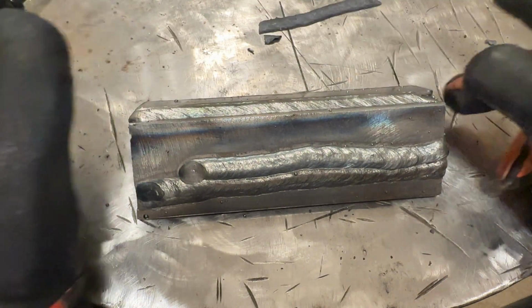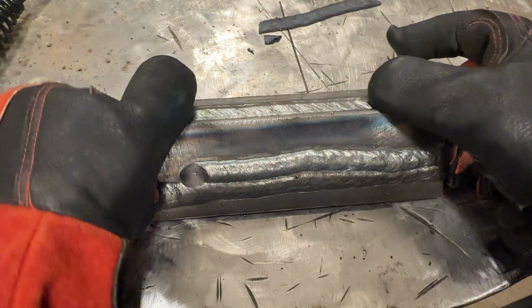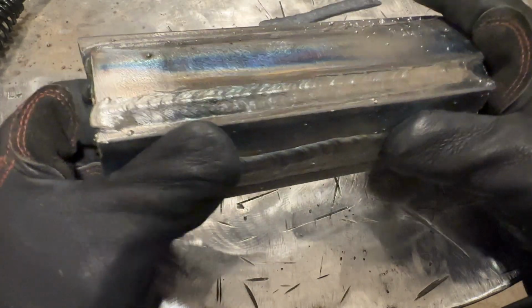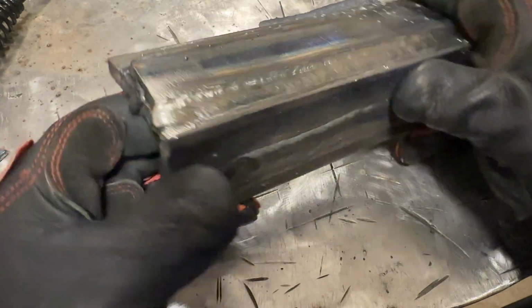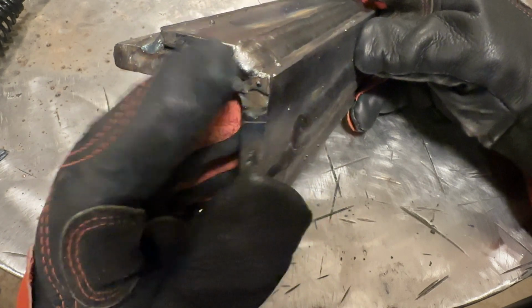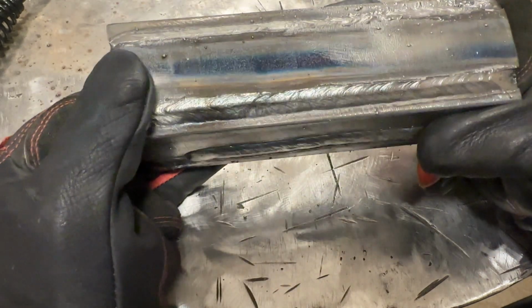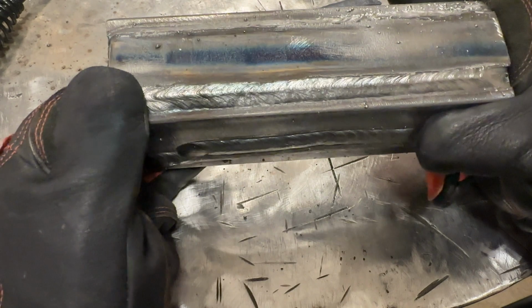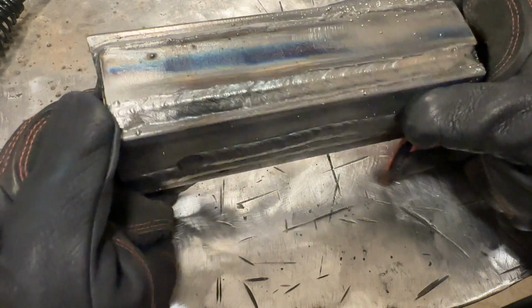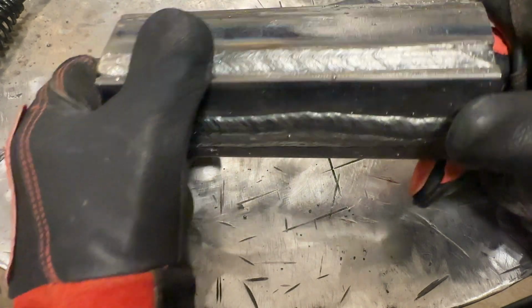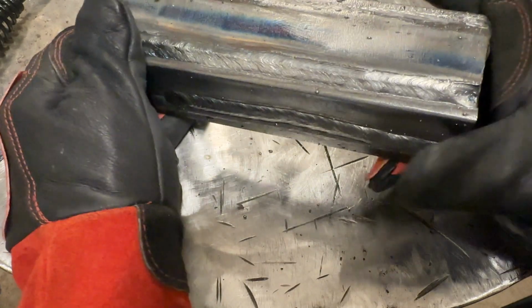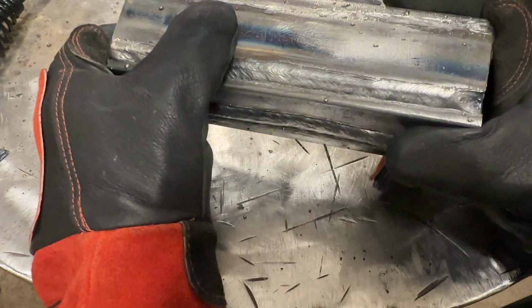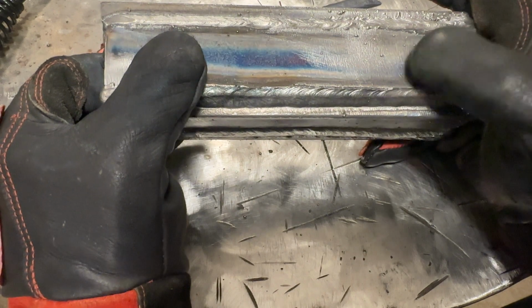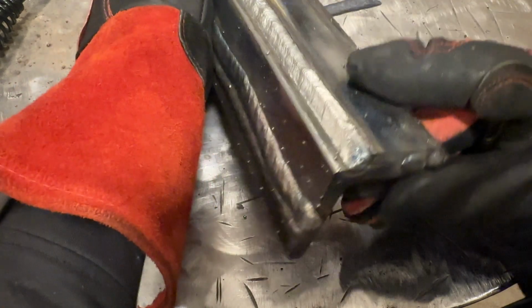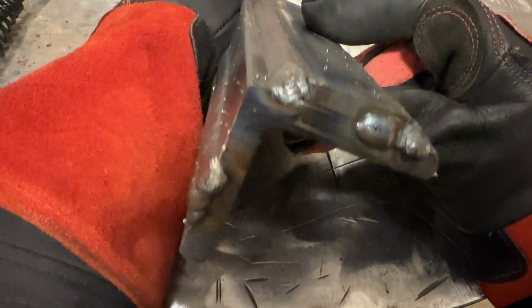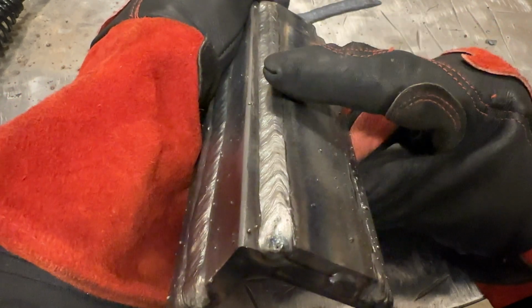Quite the slag peel, huh? I'll show you what we got here. So the first pass I did, which is on this thicker part here, 155 amps, shoved in plenty of rod. I mean, it was like melting a pretty big crayon into a hot skillet. Very nice profile, filled up right to the edge. I mean, it pretty much was melting the edge over and making it into part of the weld. If you look here, doesn't really get much better than that.